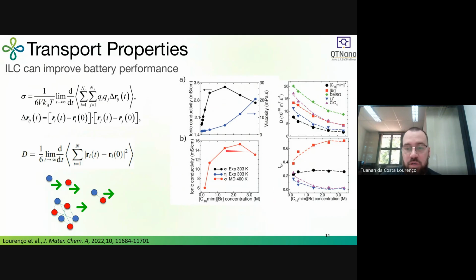So we have here at the bottom the simulation data. As you can see, as we increase the concentration of the ionic liquid, we see an increase in the ionic conductivity, and then we see a decrease. However, when we compare the two data sets, the quantitative behavior is different, the values are different, and also the point of the trade-off is different. And this is also expected because it does not matter what kind of simulation or model we are using, we are always using models, and models have their own failures and limitations. So this lack of quantitative agreement was expected.